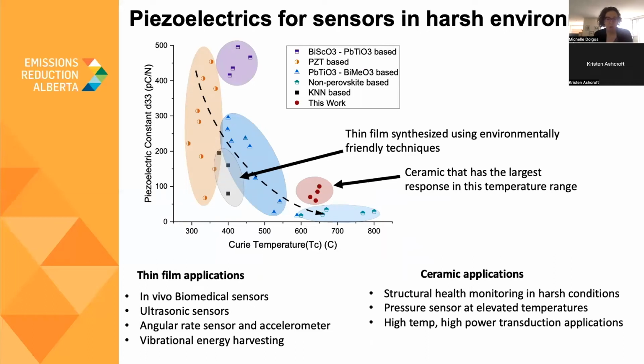So for the challenges in this space is that the industry standard piezoelectric contains lead, which is toxic to the environment, and it also has a low operating temperature. So it can't be used really above 100 degrees Celsius. But one of the challenges is that the piezoelectric response, so how well it responds to the stimuli, is inversely proportional to its maximum operating temperature.